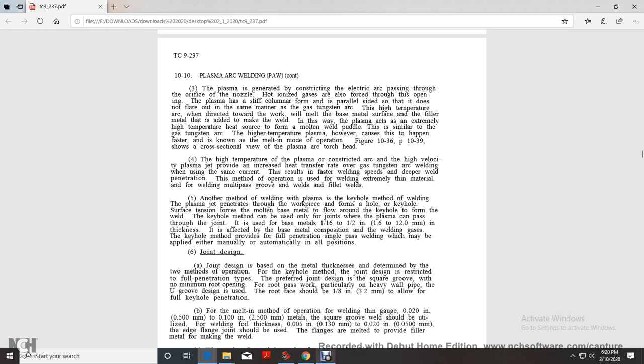Another method of welding with plasma is the keyhole method. In the keyhole method, the plasma jet penetrates the workpiece and forms a hole, or keyhole. Surface tension forces the molten base metal to flow around the keyhole to form a weld. The keyhole method can be used only on joints where plasma can pass through the joint. It is used on base metal from 1/16 to 1/2 inch in thickness, depending on the base metal and the composition of the welding gas.